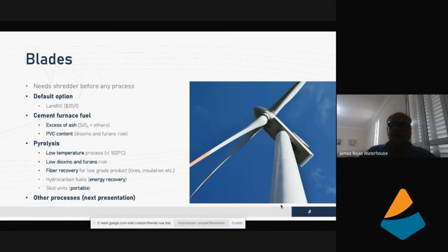And that won't be the case for decommissioning of the wind blades, just because wind blades are in the middle of nowhere, far from everything. So probably one of the best ways to do it is just take a pyrolysis unit that could be mounted in skids to the wind farm, and you can run the whole process at the wind farm itself and make it quite a cost-effective process, and bring the liquid hydrocarbons to some place else to be burned, and also the fibers. And the fibers could be reused, not for noble use, but could be reused for tiles, insulation, and other materials.